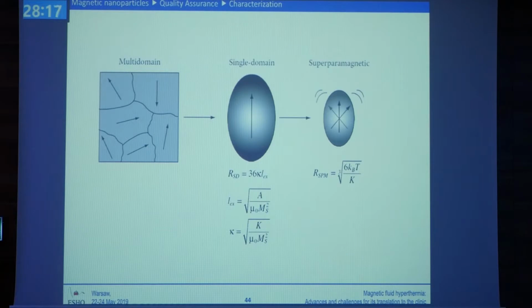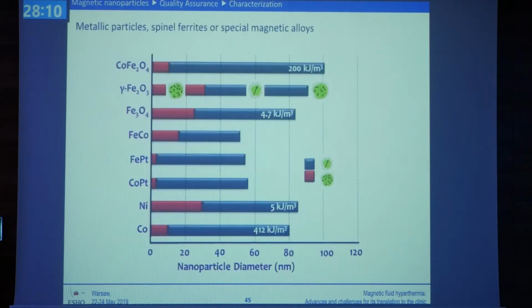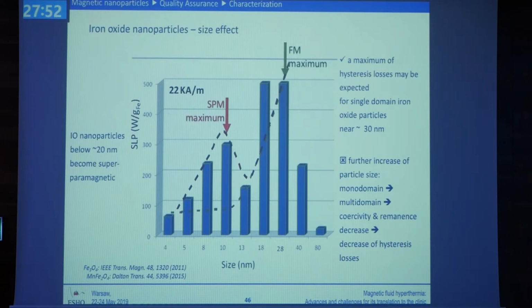The first regime is the superparamagnetic regime, the one on the right. The other two are the ferromagnetic regimes for your nanoparticles. And you can see here, depending on the nanoparticle diameter, for different nanoparticles and for different metals, what the radius is where this happens. Now, the iron oxide nanoparticles below about 20 nanometers are superparamagnetic, so the spins behave differently from each other. Then, as we increase the particle size, they become ferromagnetic, and we have a different way of depositing their energy.